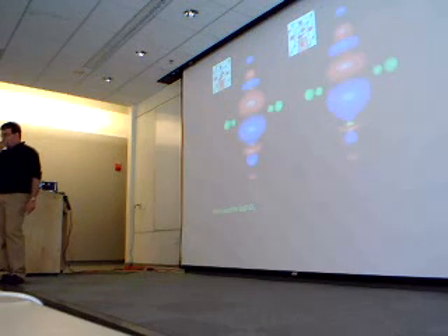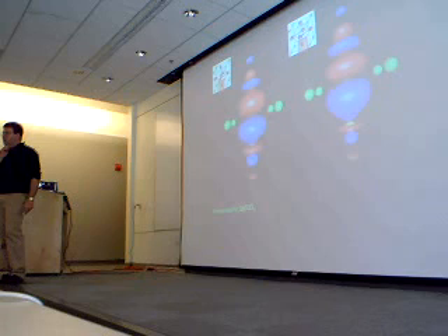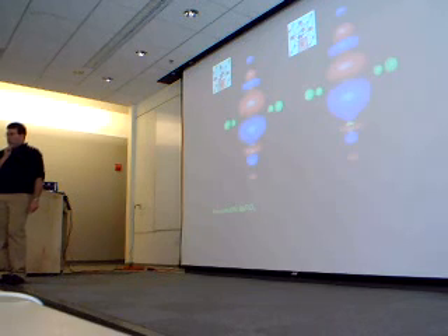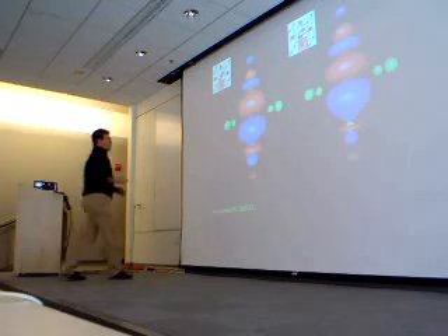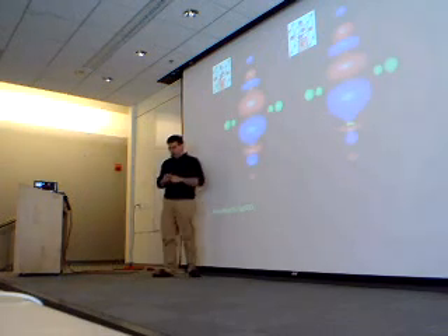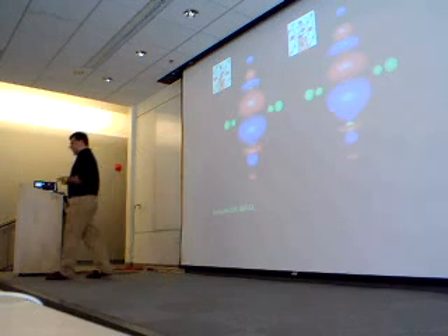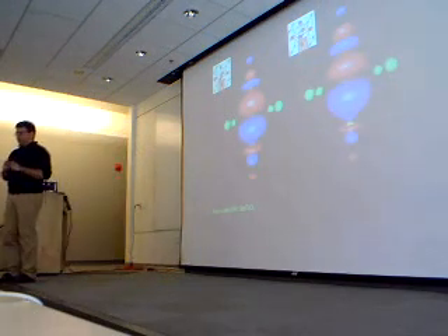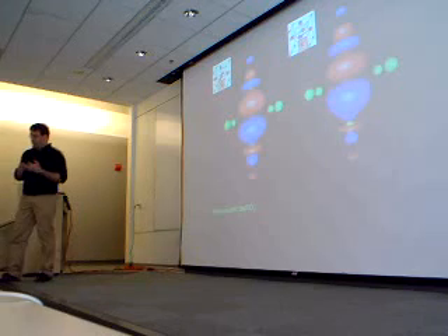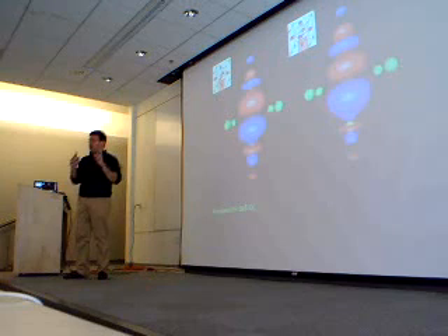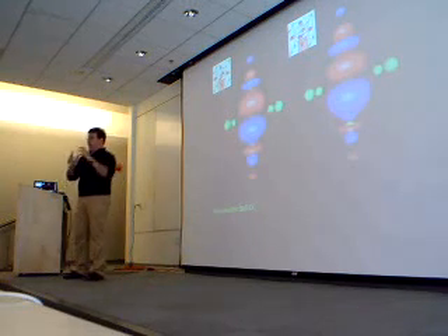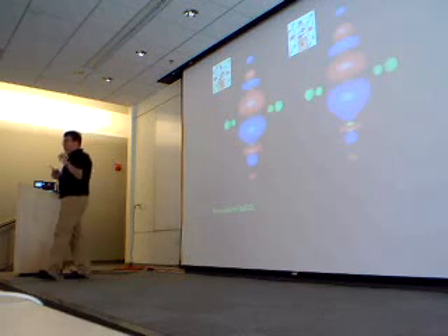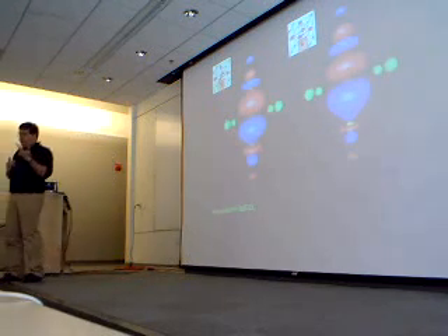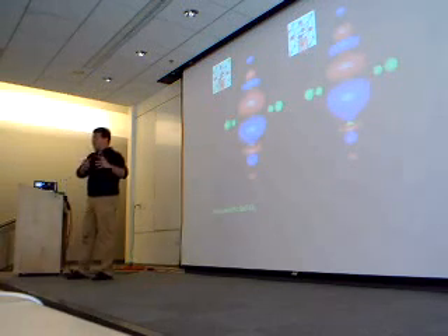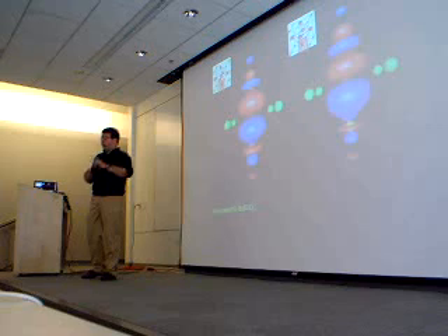Computationally, if you create a situation where this paraelectric to ferroelectric transition takes place very near to that, do you see this bond charge will be very big, very small, sometimes random, like a fluctuation? No, so the exact point at which the ferroelectric and paraelectric phase coexist is a point in which the free energies of the two phases are identical, and so in principle it costs zero free energy to transform ferroelectric into paraelectric. So what would be diverging is the dielectric response of the system, because it costs you zero to go from ferroelectric to paraelectric.